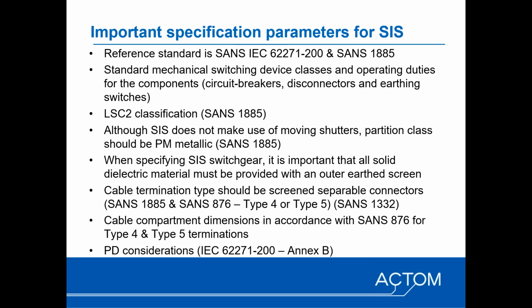And it's maybe worth noting that in 62271-200, where it covers PD testing, values for PD have not been prescribed, mainly due to the complexity and the fact that different switchgear assemblies incorporate different technologies ranging from gas to oil to air to solid dielectric. So it's very difficult to prescribe values. It is recommended, in a note, that for solid dielectric switchgear PD less than 20 picocoulombs would be appropriate, which we agree with. In our case, we're even more conservative, and we ensure that the switchgear complies with a maximum of 10 picocoulombs, so less than or equal to 10 picocoulombs.